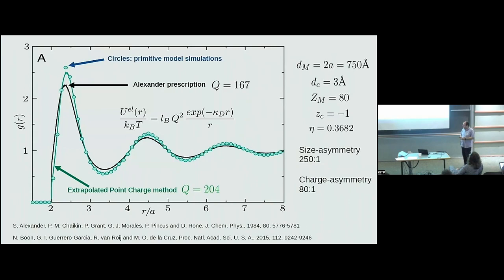There are other recipes to calculate this effective charge. Here you can observe the radial distribution functions between charged colloids. These are simulation results in which large colloids are in the presence of small ions taken into account explicitly. If you perform a simulation with ions considered explicitly and compare with the simple interaction potential, both effective charges are able to reproduce the results obtained from molecular dynamics simulations.